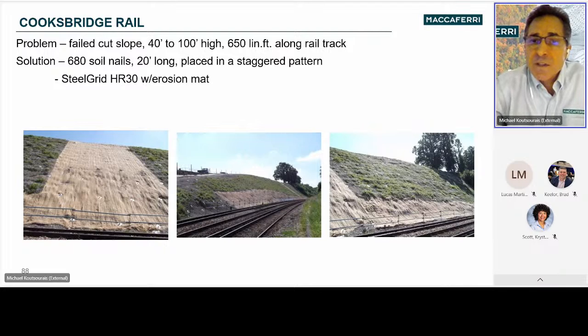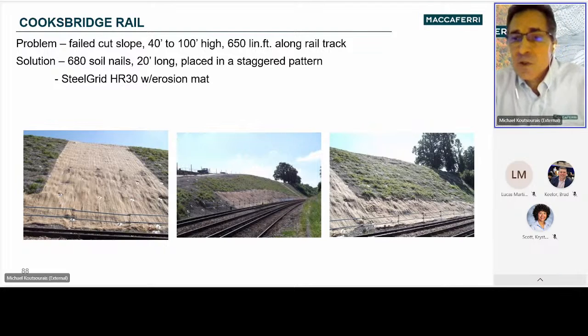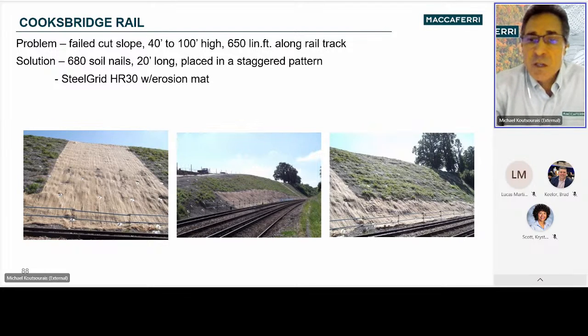Maccaferri worked closely with a designer to establish the most suitable product for the stabilization and found that the SteelGrid HR30 was deemed to be the most appropriate material, with its tensile strength of over 12,000 pounds per foot at only 6% elongation, and its in-isolation punch strength in excess of 11,000 pounds with less than 10 inches of displacement. The wire mesh was installed over a biodegradable erosion control mat to help facilitate vegetation.